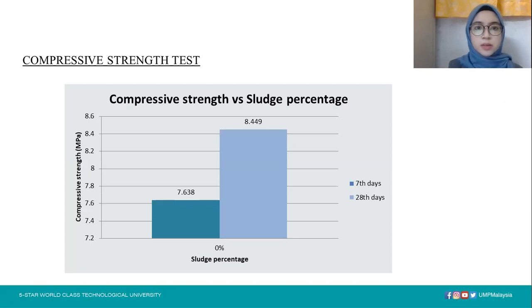Now we can see the control result for different testing days. It showed an increasing pattern when more days are taken. At 7 days, I get 7.638 megapascal, and at day 28, 8.449 megapascal. It showed that the same mixed design in different days taken increases in strength.